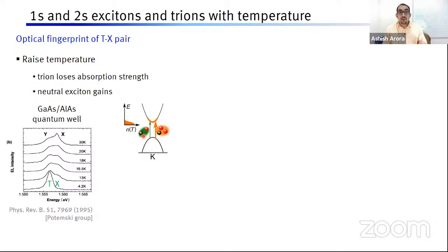Therefore, you will not be able to efficiently create the excitons. Therefore, the oscillator strength of exciton at low temperature is low, whereas for trion, it's high. Now, when you raise temperature, you have a Fermi-Dirac redistribution of carriers, where the carriers redistribute to higher energies or higher momentum states. Then at the center of the band where the optical transition takes place, the probability of creation of trions goes down because now the number of available excess carriers is less.